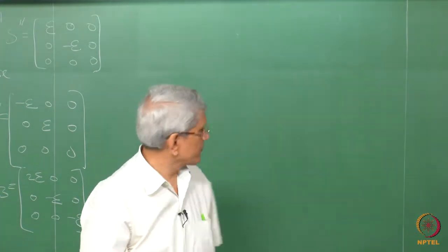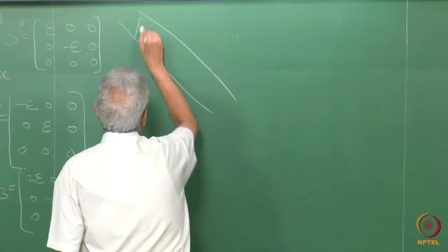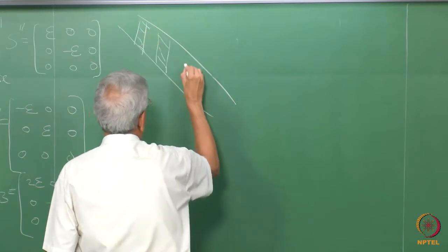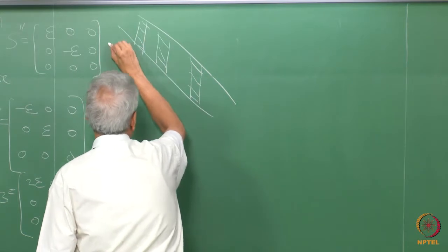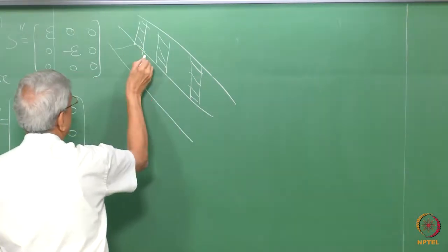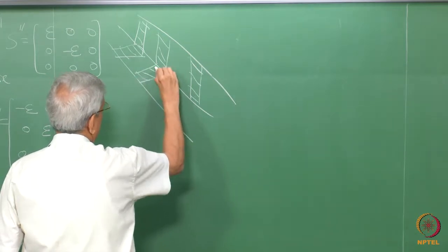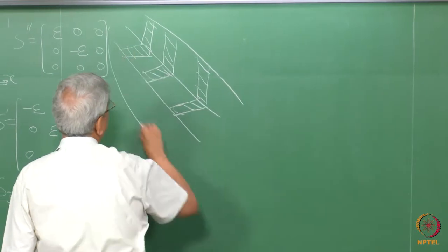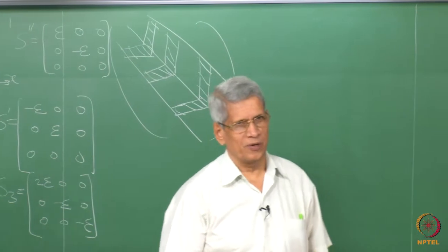That means that if we have one region where twins have formed like this, there is an adjacent region with two variants, assume that twins have formed like this. If we take these two combined regions, the total strain turns out to be 0.